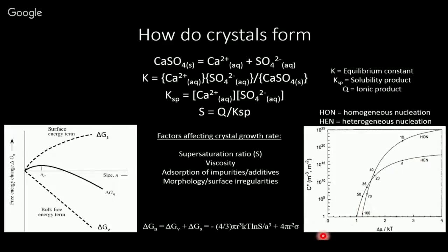So if you want controlled growth on a surface, such as making a film and not particles, you want to increase the supersaturation very slowly. You add your ions to the solution very, very slowly until you hit this range where you have a very controlled surface process. Otherwise, if you do it very fast, you're going to get homogeneous nucleation, because it is more favored at higher values of supersaturation.